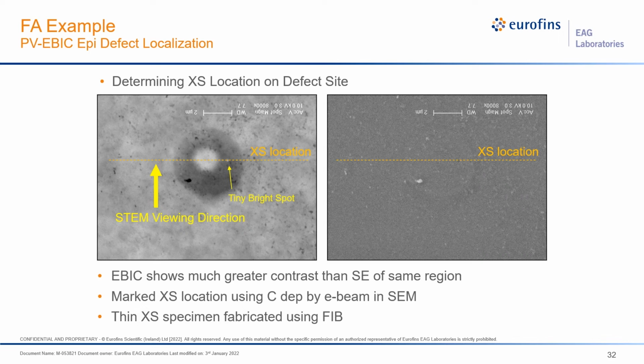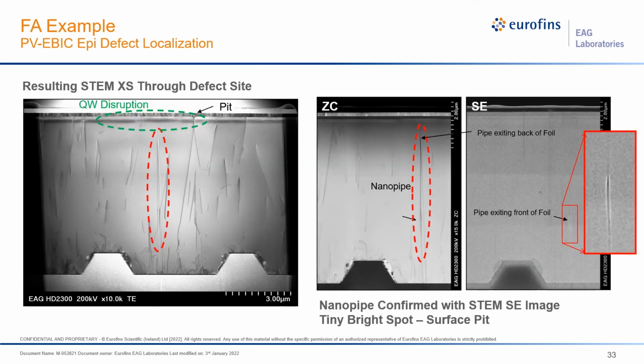So now you're seeing in cross-section that same location across the defect, and we identify that there's three main features here. We see that there's a quantum well disruption up here near the surface. There's this vertical feature here, as well as we can actually see a pit in the ITO over here to the right. So for this vertical feature, we can actually identify this now as a nanopipe in the structure.